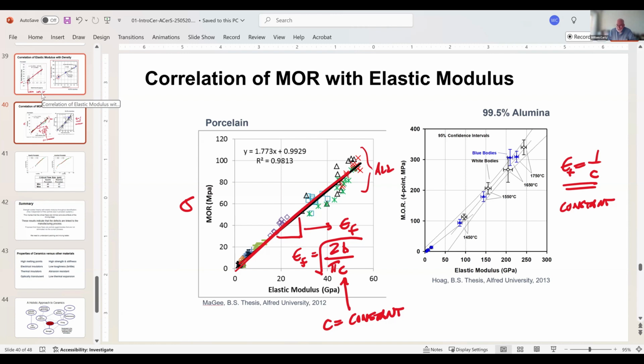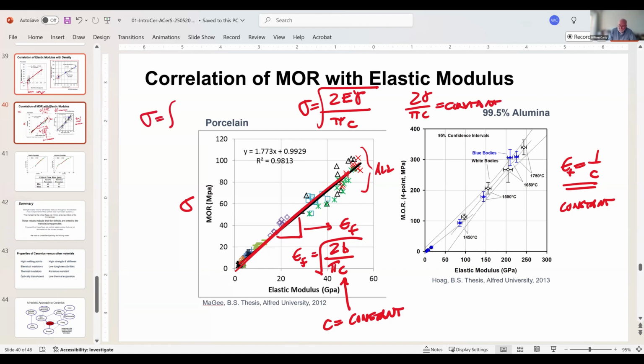And by improving my elastic modulus, when I go back to Griffith's equation, sigma is equal to 2 elastic modulus times fracture surface energy divided by pi c, all under the square root. If 2 gamma over pi c is constant, right? I increase my strength, sigma then scales as a function of elastic modulus. It is no longer a function of flaw size.